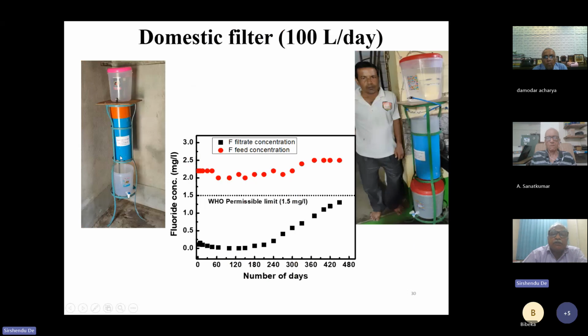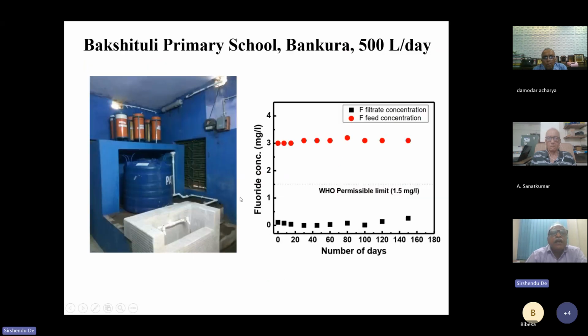It is around between 2 to 2.5 milligram per liter, and the filtrate it increases. And this particular filter was designed for 1 year. So if you look into the performance, this is below that permissible limit. It is still permissible. It was working fine up to 450 days. Okay. After that, the filter media will be changed.